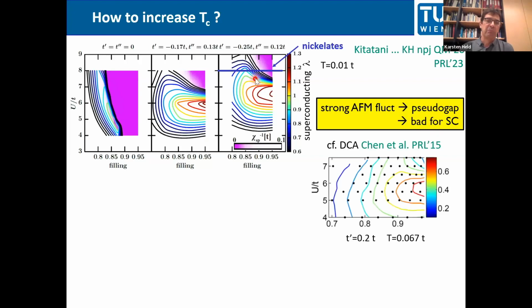So very similar fingerprints have also been calculated in DCA by Emmanuel Gull and company. They couldn't go to such low temperatures, but it's a very similar kind of fingerprint as we get here, with slightly smaller lambda parameters or superconducting eigenvalues yet. Now, to reach this sweet spot for superconductivity, we actually have to decrease U, or we have to increase T, which is much easier in experiment.